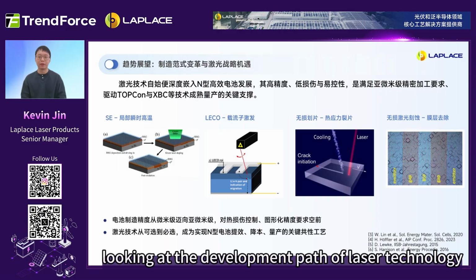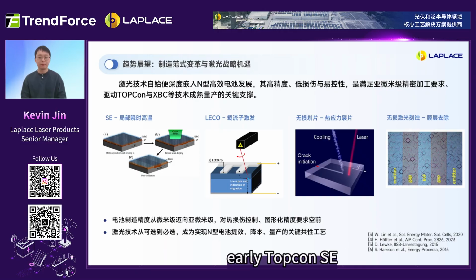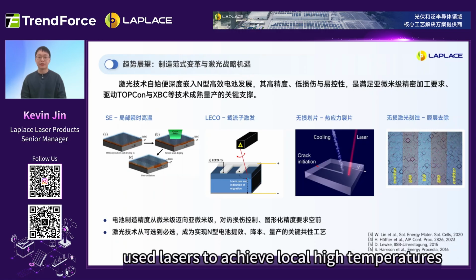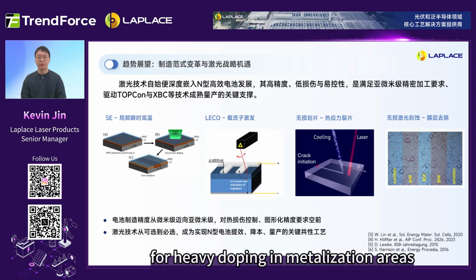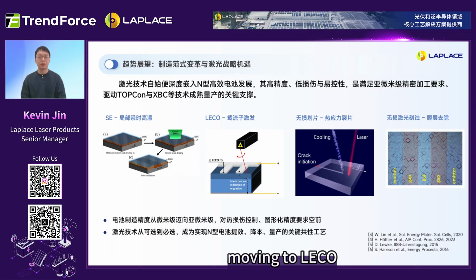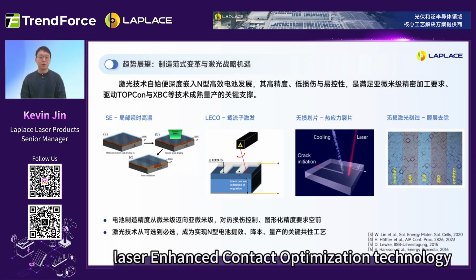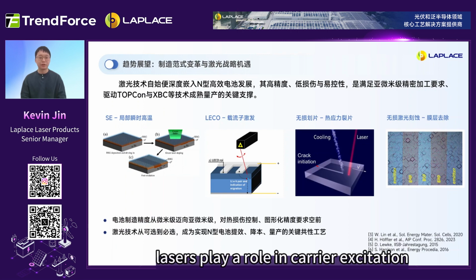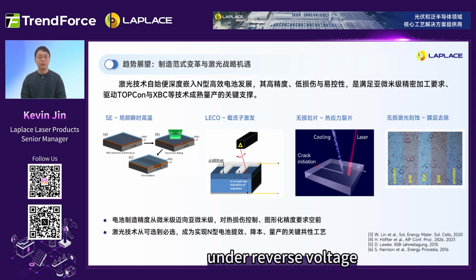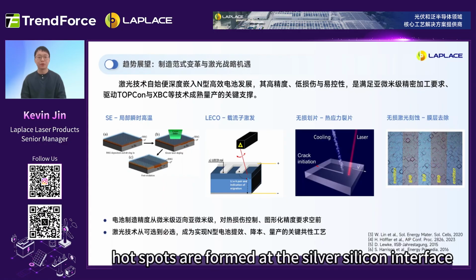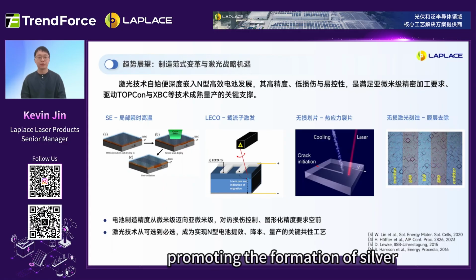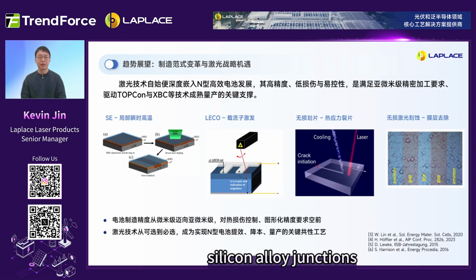Looking at the development path of laser technology, early TOPCon SE, selective emitter, technology used lasers to achieve local high temperatures for heavy doping in metallization areas. Moving to LECO, laser enhanced contact optimization technology, lasers play a role in carrier excitation. Under reverse voltage, high current density local hotspots are formed at the silver-silicon interface, promoting the formation of silver-silicon alloy junctions and reducing contact resistivity.